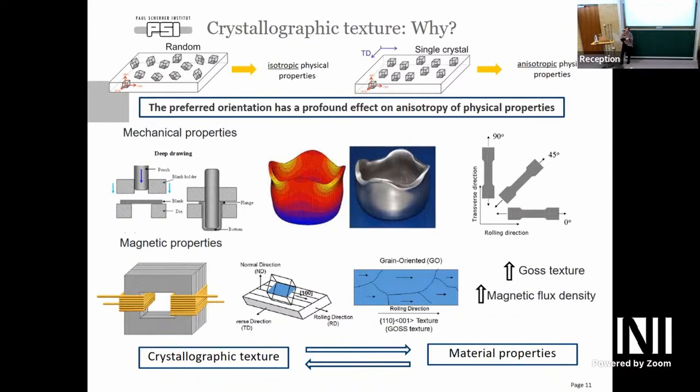We can assume the other way: a single crystal can also be represented as an orientation distribution function when you use just a delta function inside your model. So in that sense, the orientation distribution function could be whatever you like. It could be a delta function in your space, or it could be a small function. A delta function is essentially associated with a point. Exactly, and that's the extreme.